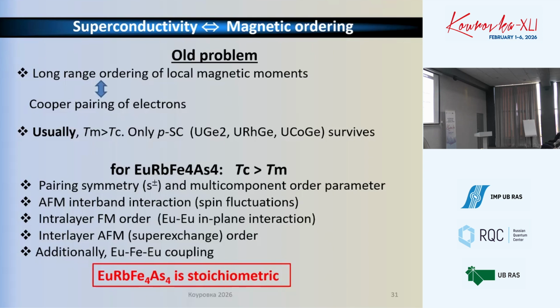But here we have a different case. In this compound, the superconductivity is stronger than the magnetic ordering. Because of the layered structure, the europium layers are far away. Therefore, the coupling is weak. So the magnetic ordering should emerge inside the superconducting state.